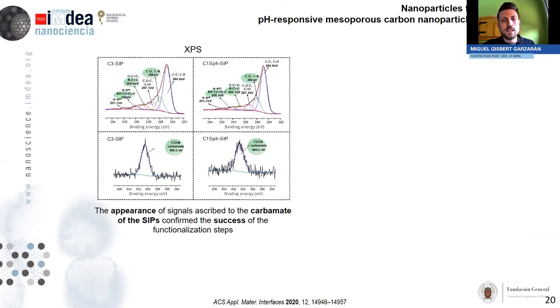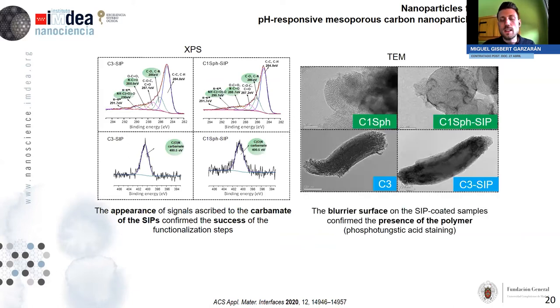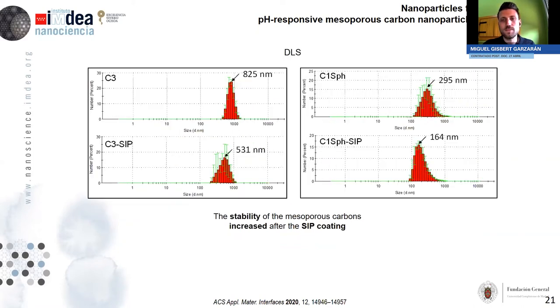Using again the XPS, we could observe the presence of signals that were ascribed to the carbamate of the self-immolative polymers. In addition, this is interesting because using the transmission electron microscope, not only can we observe the nanoparticles, but we can also observe if there is organic matter on the samples. This can be done using phosphotungstic acid, which is a compound that stains the organic matter. So again, we could see the organic matter.